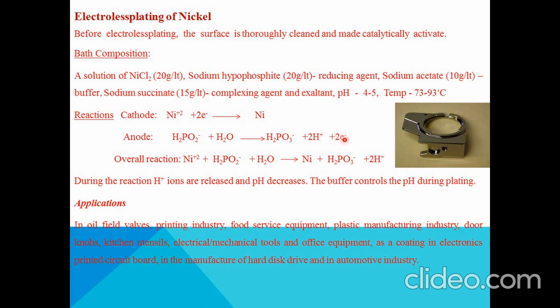The electrons released by the reducing agent are taken up by the nickel ions, which then undergo reduction to form nickel atoms. The nickel atoms deposit on the surface of the substrate. This is the cathodic reaction and this reaction also takes place on the surface of the substrate. The overall reaction is like this: nickel ions reacting with sodium hypophosphite in the presence of water to give nickel atoms and sodium phosphite, releasing H plus ions. Because of the release of H plus ions, the pH decreases. In order to maintain constant pH, the buffer is added.